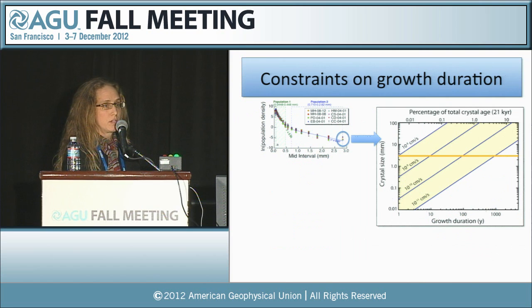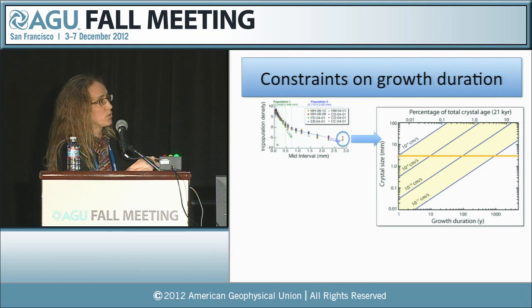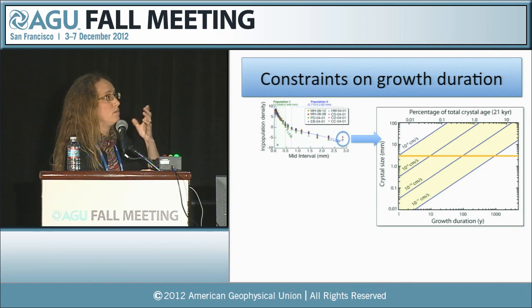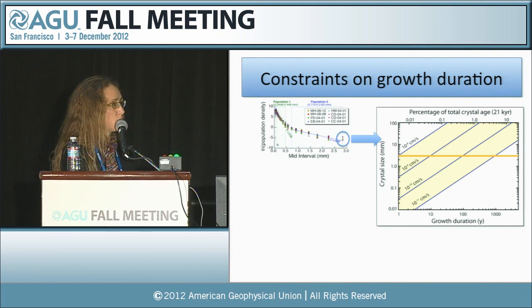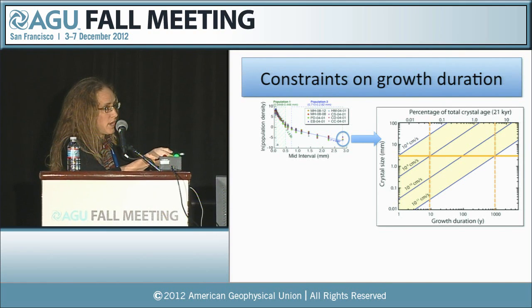So we can also get some constraints on the total growth duration, and one of the simplest ways to do that is simply to take the largest observed crystal size of about 3 millimeters and then assume some crystal growth rates. So these are typical plagioclase growth rates. And then calculate how long it would have taken to grow a crystal of that size. And so the growth durations that we get for, say, 10 to the minus 9 centimeters per second would be on the order of a decade. For very slow plagioclase growth rates of 10 to the minus 11, it's on the order of 1,000 years.